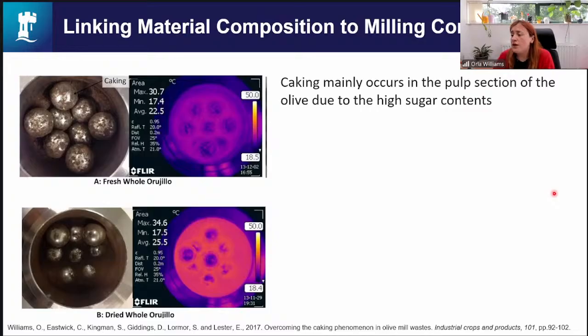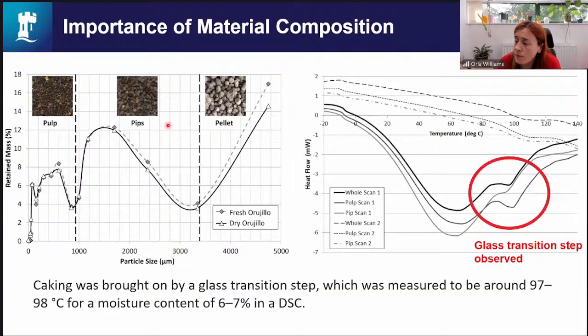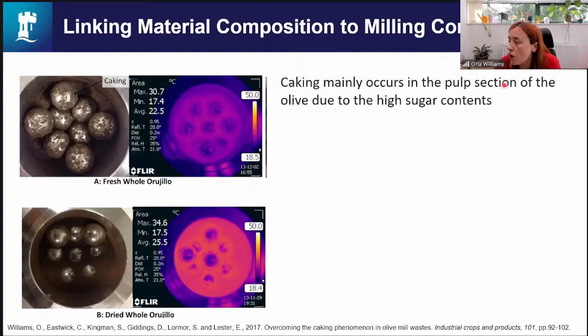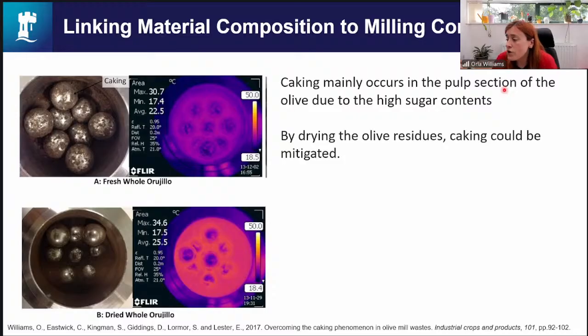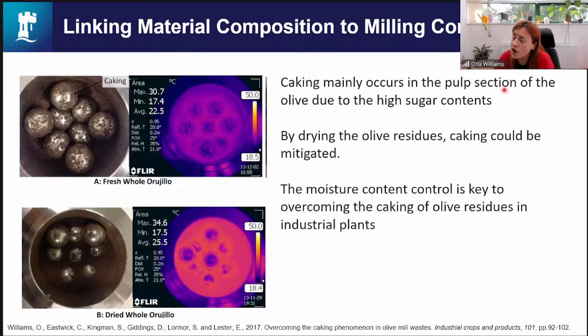You could actually see the heat being generated in the mill through thermal imaging. We see lower heat generation within the mill when you're using the wet material than when you have it dry. We also milled each section of the olive: the pulp, the pips, and the pellets individually under the same conditions, and we milled them as a whole. We found that the caking was only really happening in the pulp section of the olives. This was due to the high sugar content of the olives, which is actually variable by season. But by drying these olive residues, you could remove this caking issue. So moisture content was key to overcoming the caking of the olive residues in the industrial plants.